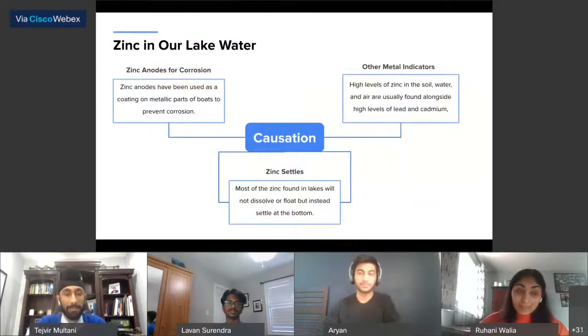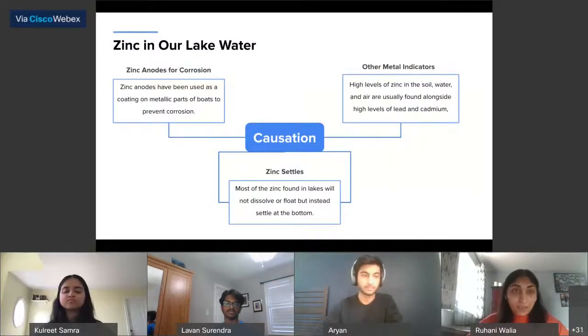Moving on to our next element, the presence of zinc in the lake water samples was insignificant in comparison to the tap samples. From a health perspective, we found that zinc is an essential element and is generally considered non-toxic to humans. So swimming in a lake, for example, with low concentrations is not harmful. To explain why we found zinc, anodes have been used as a coating on metallic parts of boats for several years to prevent corrosion, which may explain small amounts of zinc in lakes.